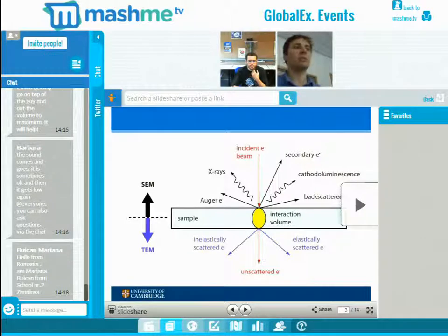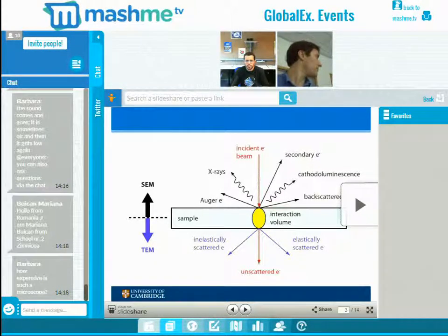The only thing that sometimes is tricky is if you look at cells, because they have water inside, and as I mentioned before, the whole SEM chamber is under high vacuum, and then typically the cells just start to blow up, but there's a way around that. You can keep gas inside the chamber, so you don't do the really good vacuum. You can also look at cells, or you can freeze the cells, for example. Yep. Let's go to the next slide.